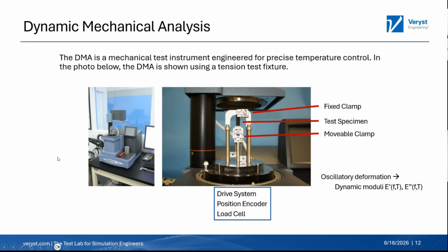And tools that you can use to measure the thermal properties of these polymers that are relevant to thermoforming. The one I like to talk about first and like to talk about the most is dynamic mechanical analysis, or DMA. This is the measurement tool that even if you're not looking at a thermoforming polymer, I strongly recommend folks get a DMA temperature sweep done on essentially any plastic that you're using in your device, because it reveals lots of useful information that we're going to talk about in a little bit more detail. But fundamentally, the DMA is a mechanical test. We have a sample, it's in black here, that's in a tension grip. There are other grips that you can use.